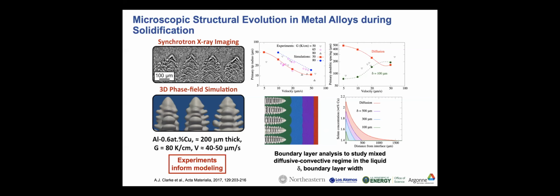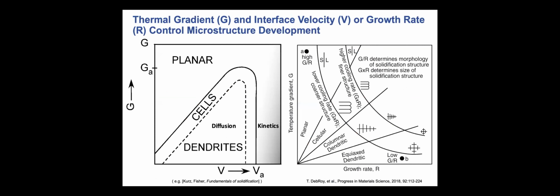And so here what we did is we artificially truncated the solutal boundary layer. And when we go down to 100 microns, like that shown in green, we now get good matching with experiments. So I really like this example because it highlights from these dynamic kinds of experiments that we can actually start informing the physics that's missing from the modeling. And again, this is true even in these thin constrained 2D sample geometries at 100 microns or 200 microns as an example.